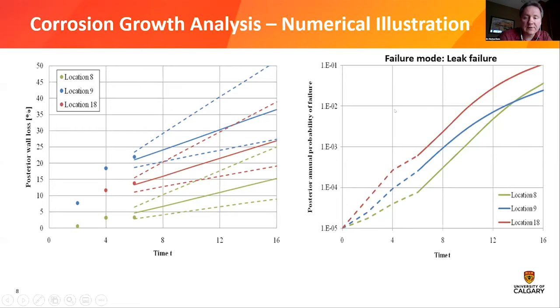So here on the right, I have an example where those defects on the left were assessed in terms of leak failure. And then we can estimate the probability of leak failure as a function of time. So as the defect grows over time, we see the probability of failure increases. And then if it's a reliability-based assessment, we can say, okay, once we hit our maximum allowable failure probability, that's a time, or before that, we have to intervene.